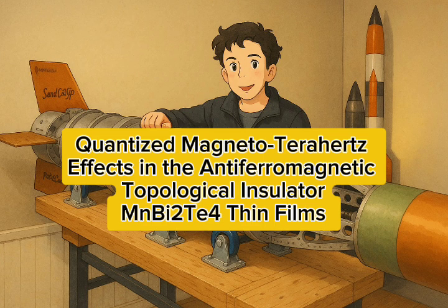Yes, but here's the twist. When you stack these septuple layers, the magnetic direction flips between adjacent layers. Layer 1 points up, layer 2 points down, layer 3 points up, and so on. So they alternate, like an antiferromagnet. Precisely. It's called A-type antiferromagnetic ordering. Ferromagnetic within layers, antiferromagnetic between layers.